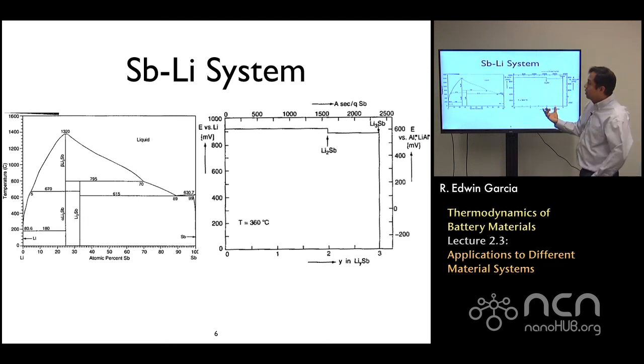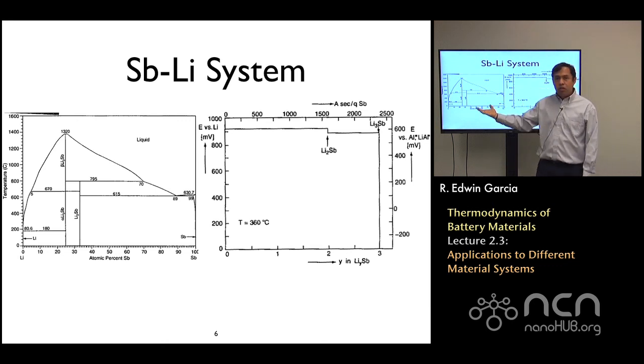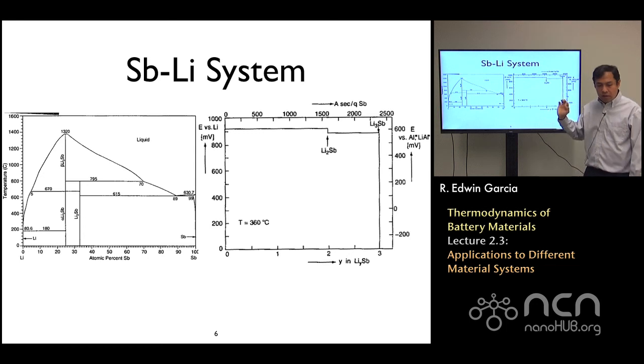Clearly showing you, again, the same type of behavior, and how when we are really measuring the voltage of a battery, as this voltage goes through these different stages, these different plateaus, what we're really doing is measuring the phase diagram of the system, if we do it, in this case, very slowly.